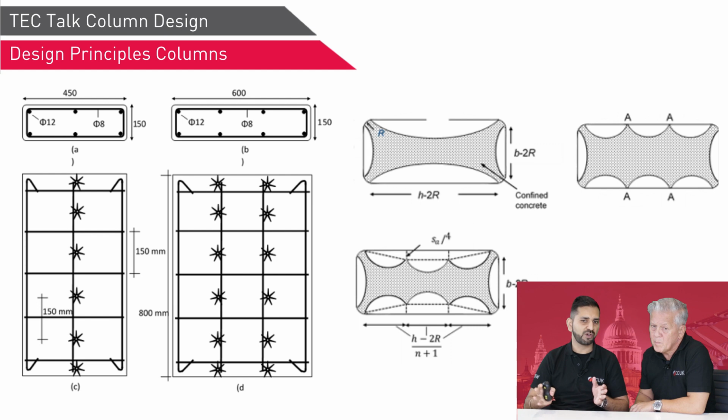Your corners will push out first, and your confinement in the middle will not be effective. So what we can do, we can use the carbon fiber anchors, either one anchor in the middle if this is on the smaller size, and two in the longer edge. So it becomes like a small kind of column. So here now the confinement becomes fully effective because you've got these anchors.